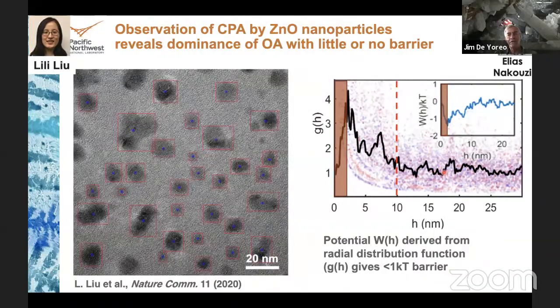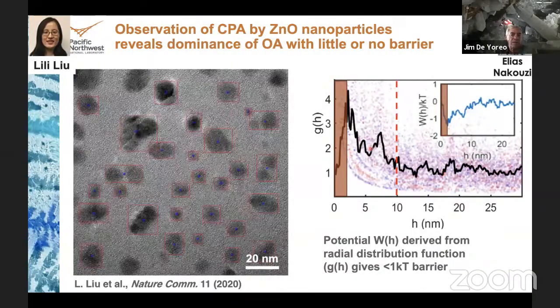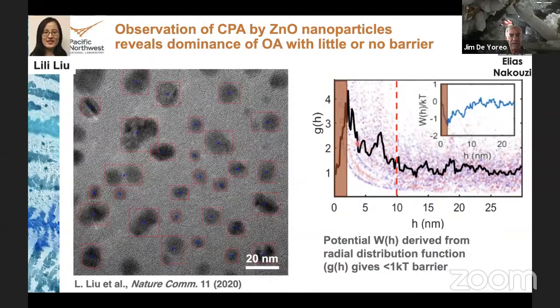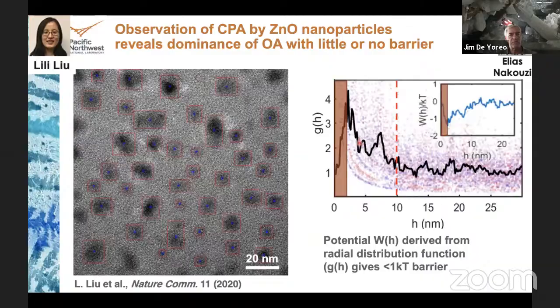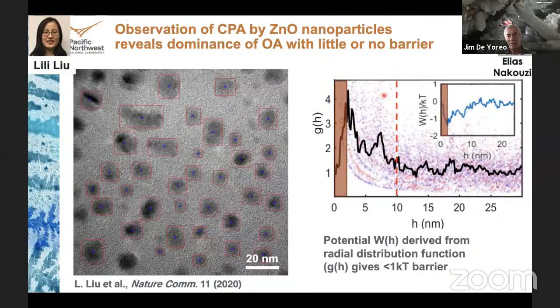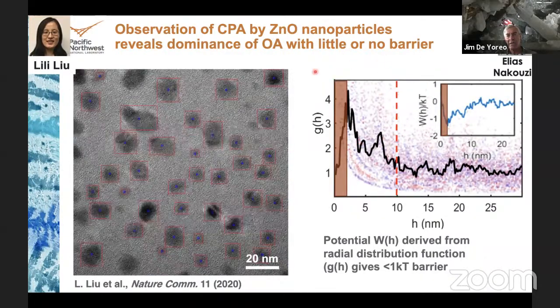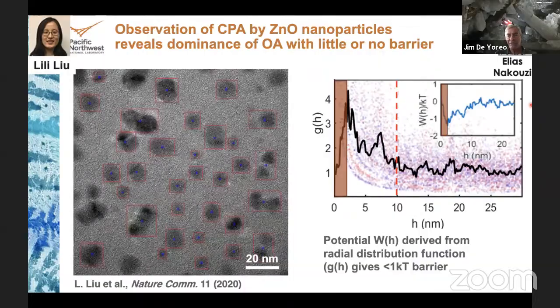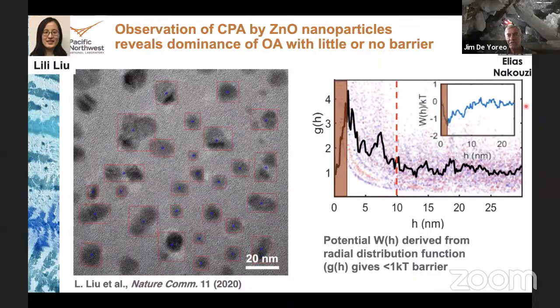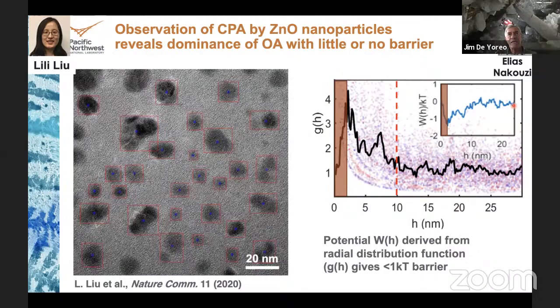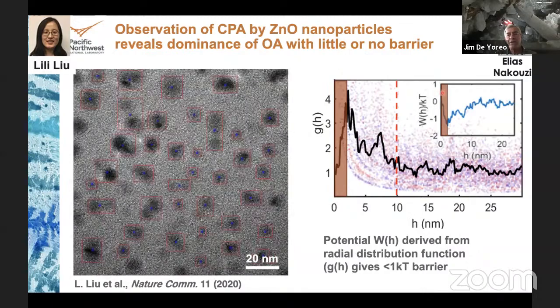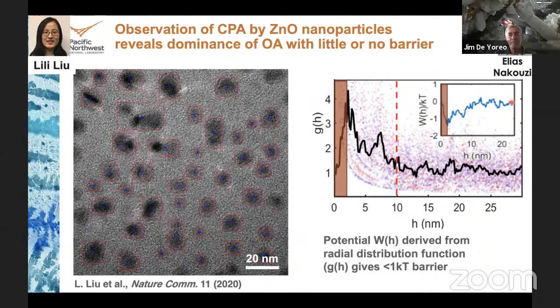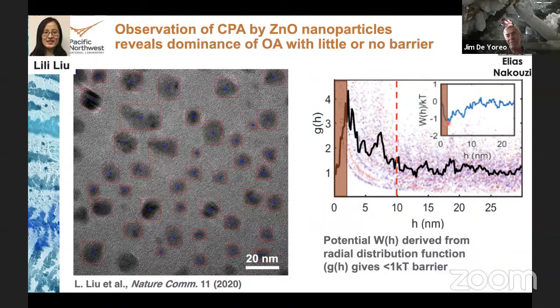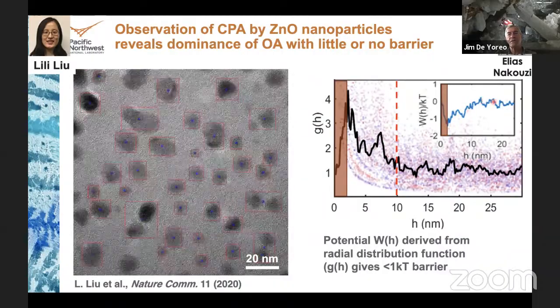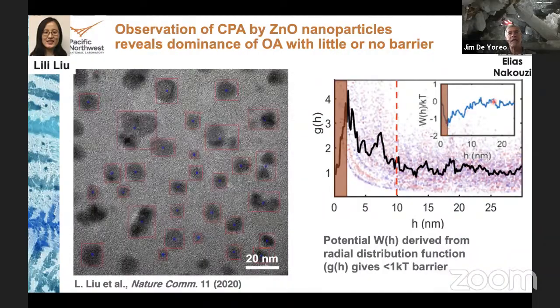Now, we can invert this to an interaction potential because, of course, the probability of particles being in any given location is exponential in the free energy as a function of the distance from other particles. And so this is what the potential energy versus distance looks like. And what you see is, this is in kT, right? There are no barriers. It's a smooth drop to contact. And I mean, maybe there are some barriers, but within the noise in our data, they're certainly not larger than 1 kT.